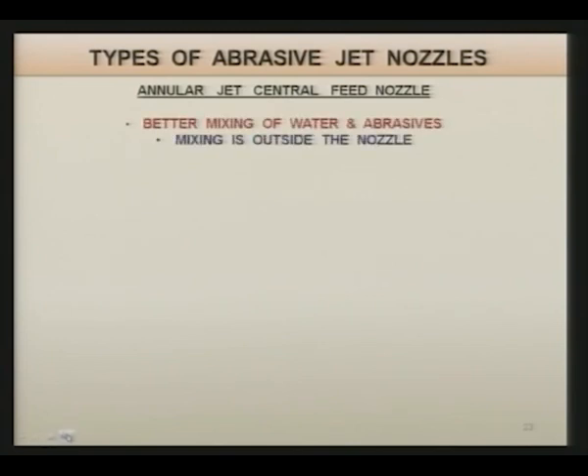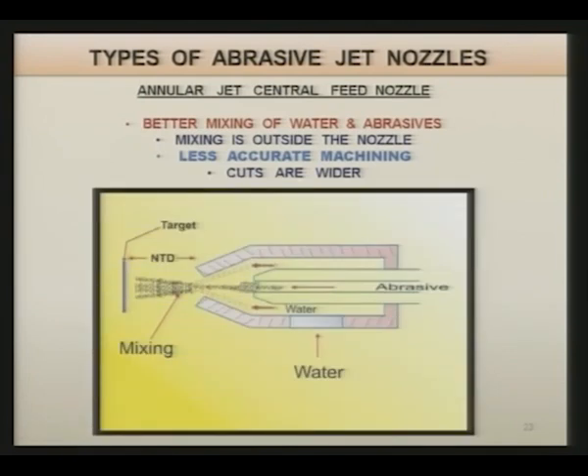Another one is known as the annular jet central feed nozzle. It gives better mixing of water and abrasive, but in this particular case mixing is outside the nozzle. It gives less accurate machining as compared to the earlier one. In this case the cut or kerf width is higher compared to the earlier one. As you can see here, water is coming from the sides and abrasive is coming from the central port. Both of them are mixing here outside the nozzle, and you can see the divergence, and because of this divergence of the abrasive water jet, the accuracy of the cutting reduces compared to the earlier type of nozzle.